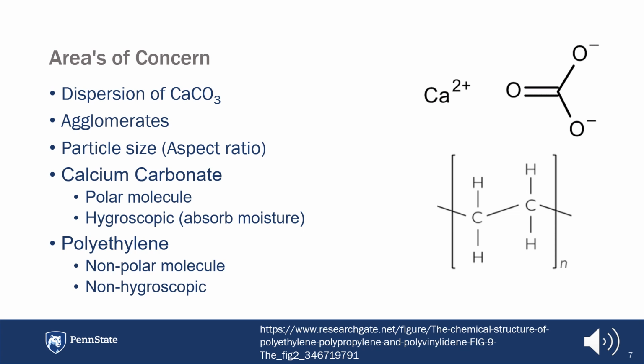So this makes these two materials not compatible for processing, meaning if we were to take polyethylene and calcium carbonate, mix them together and process it, we'd get a lot of pellets with some calcium carbonate and some with none. So to compatibilize these materials, we coated the polyethylene in mineral oil, and then we poured on the calcium carbonate and then mixed it and then processed it.